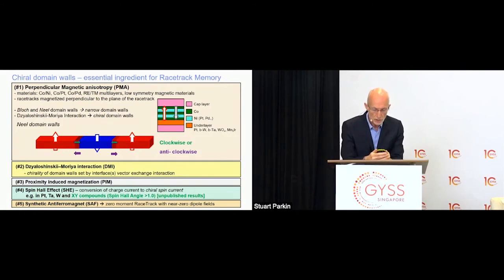The chirality can only be changed by changing that orange material. If we change it from platinum to tungsten, for example, the chirality would be different, but the chirality would be the same in all the domain walls. And this is the only reason why all those domain walls will then move in the same direction when we pass current pulses through that platinum layer, which generates this spin Hall effect. Now, other elements of making racetrack very important are that the platinum typically will become itself slightly magnetic by a proximity-induced magnetization. And this synthetic antiferromagnetic concept is very important.